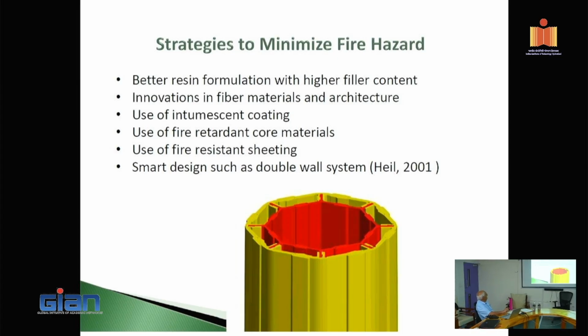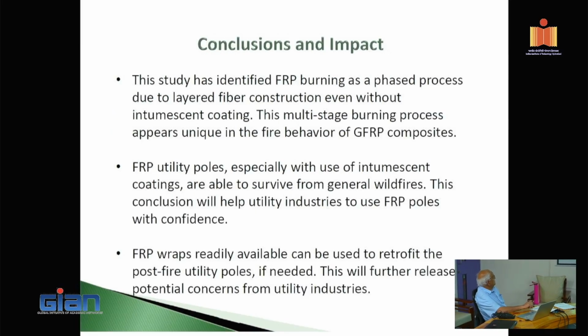Okay. This is a double wall pole. I won't go there. In conclusion, this study has identified FRP burning as a phased process due to layered fiber construction, even without intumescent coating. This multi-stage burning process appears unique in the fire behavior. Utility poles are able to survive general fires, and in conclusion, we can see that this will help the utility industry to use the FRP poles.